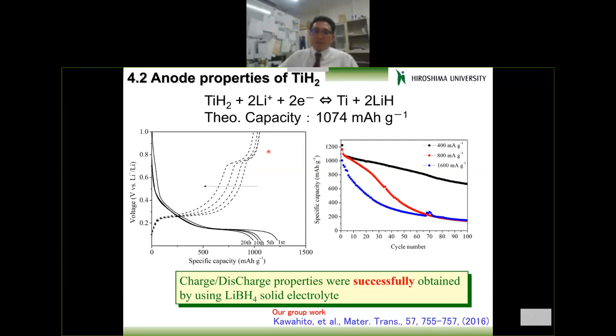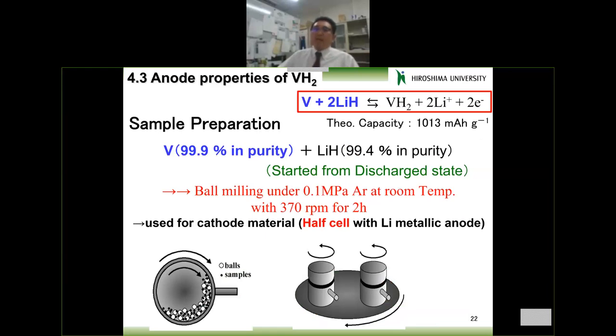But anyway, we observed at 0.2 volt or 0.3 volt, one clear plateau existing, successfully observed using lithium borohydride solid electrolyte. This is also reported here. Cycle property is slightly worse, but somehow we observed this anode property. And the final topic is vanadium hydride. And of course, as I mentioned already, vanadium hydride is quite difficult to keep without a hydrogen atmosphere.